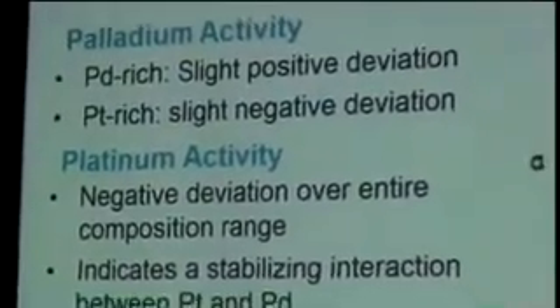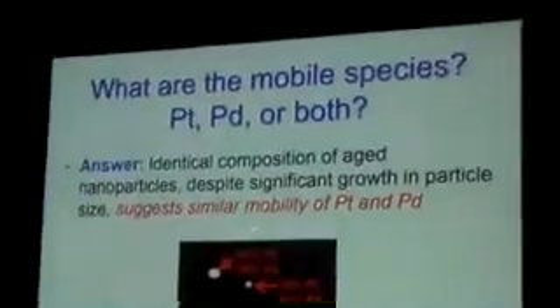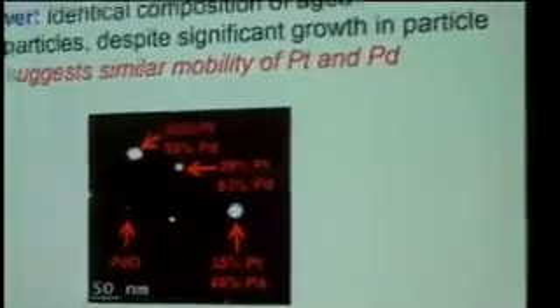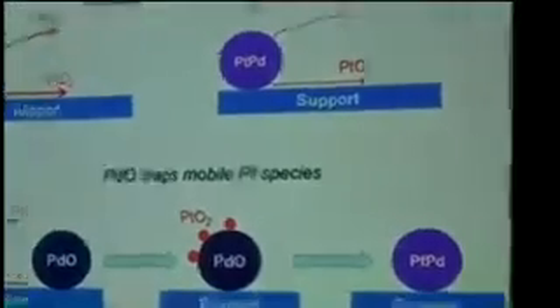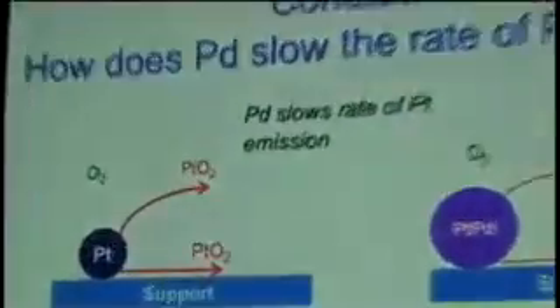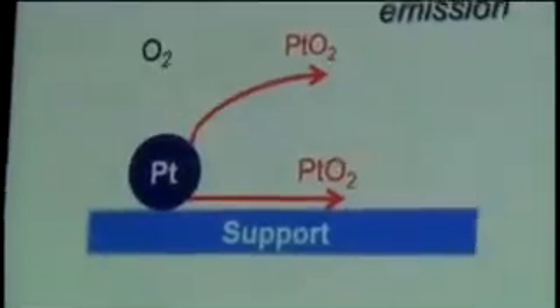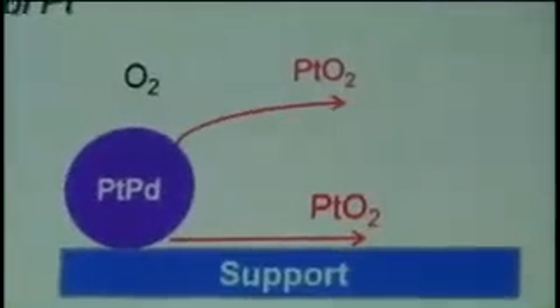So we are cutting down the emission, and at this point it suggests that the surface diffusion, both species are moving, which is why as the particles grow larger in size, the composition stays the same. We do not see phase segregation, and that is the reason why this catalyst works so well, because we think this is the crux of the matter. The palladium oxide is like a trap. It is trapping the mobile platinum species and preventing them from going into vapor phase. And thereby, it slows the rate of sintering by keeping these platinum palladium particles.